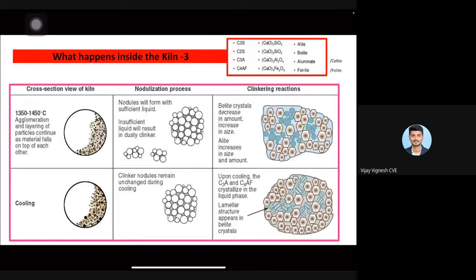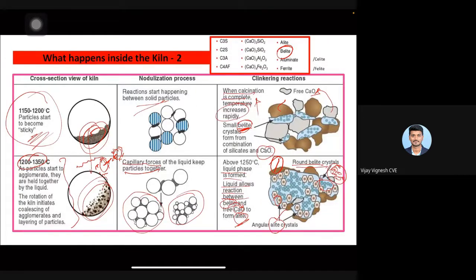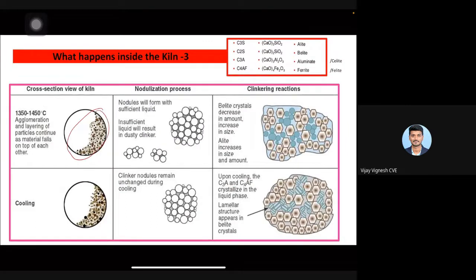Around 1350 degrees centigrade to 1450 degrees centigrade, agglomeration and layering of particles continues as the material falls on top of each other. You can see here, after this it may fall here and there. Then the nodulation process will form with sufficient liquid. Insufficient liquid will form dusty clinker. So it can be a boulder like this. So insufficient liquid forms dusty clinker.